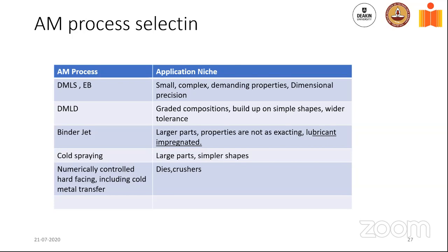I forgot to talk about cold spray. That's an important mechanism as well. It's an offshoot of thermal spraying, except that you don't melt the particles. The powders are shot not at room temperature, but at, let's say, 400 to 500 degrees Celsius, and at a velocity of around 1,000 meters per second, and that works brilliantly.